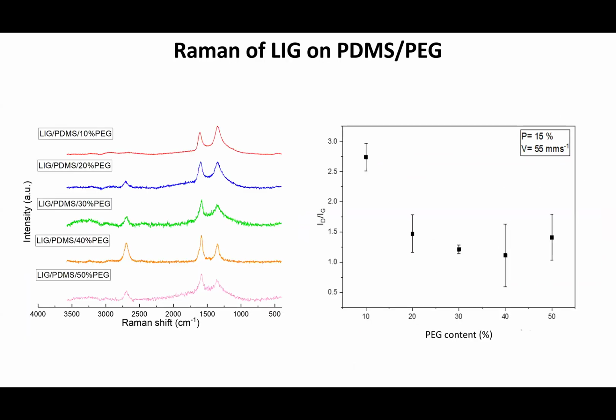Again, we performed Raman spectroscopy to check the quality of this, and we see this trend again as you add more PEG to the PDMS matrix. You, let's say, increase the quality of the graphene, with the difference that in this case there seems to be an optimal content of 30 to 40% of PEG. If you go beyond that, your samples become inconsistent. They become kind of mushy, so it's not really something you can use.